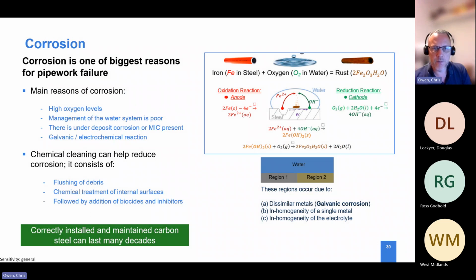And corrosion is pretty well understood. It's one of the biggest reasons for pipework failure based on the data which we've got. However, we do know the reasons behind corrosion: open systems, closed systems. An open system is going to have more oxygen in. However, closed systems can also have the same amount of oxygen in, particularly if they're leaking or somebody hasn't made sure that system is leak tight. So again, understanding what we call the electrochemical reaction, where oxygen plays a key element.